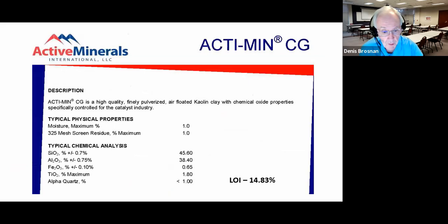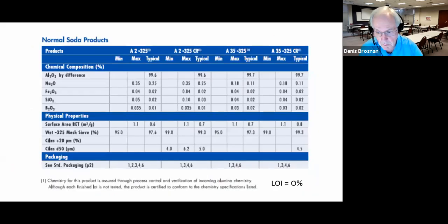And we're going to mix it with clay, and you've already seen this data sheet, catalyst grade kaolin. I don't believe it's commercially available now. That's what I used in my laboratory experiments. It has a loss on ignition of about 14.8%. That's important to know, and we're going to add it to calcined alumina. You've seen this data sheet from the last class, and loss on ignition is nil, negligible for that.